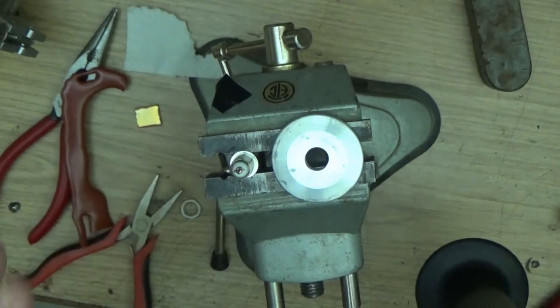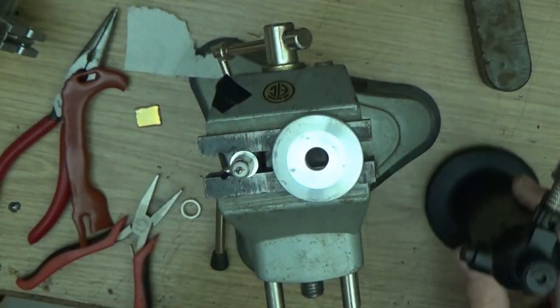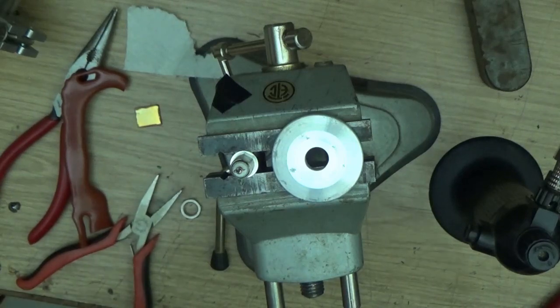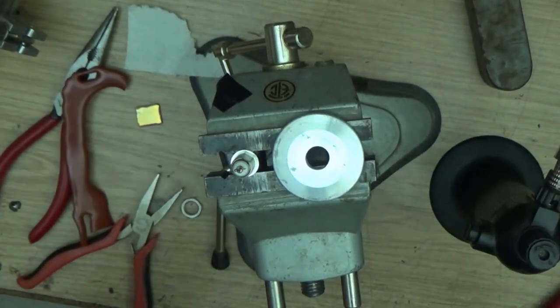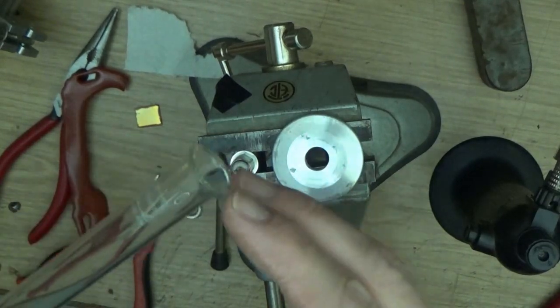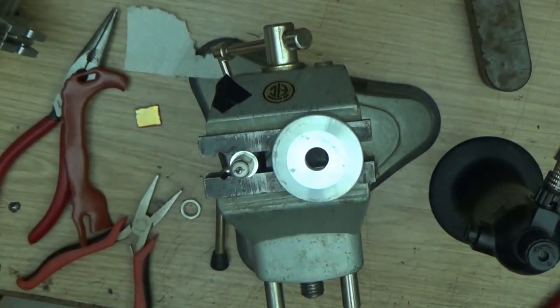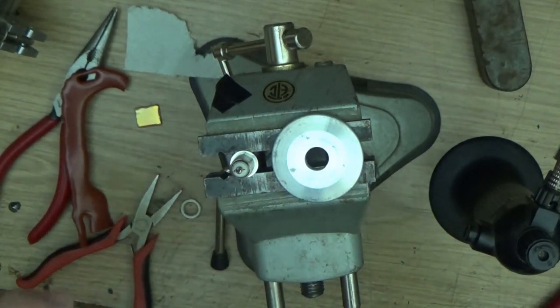Obviously, you can only do this to materials that stand being torched. Maybe you could preheat them in an oven. I don't know. I haven't tried. But generally for a vacuum, if it can't stand heat, then you don't really want to use it anyway. So if you seal glass to metal, make sure it's borosilicate glass like a piece of test tube glass or a specific borosilicate rod. Don't just use thin window glass. Okay, let's try and seal these surfaces.